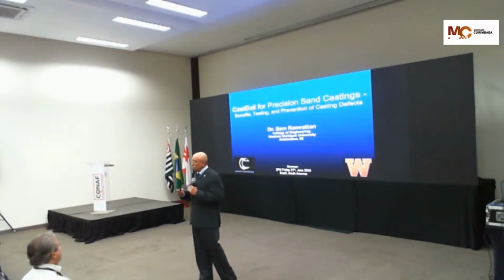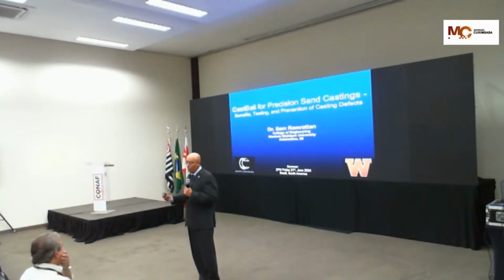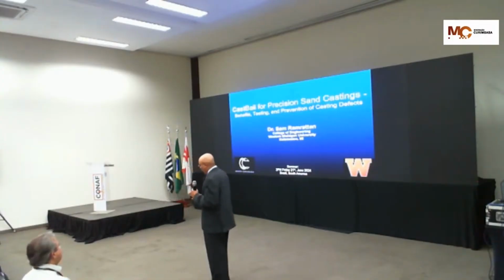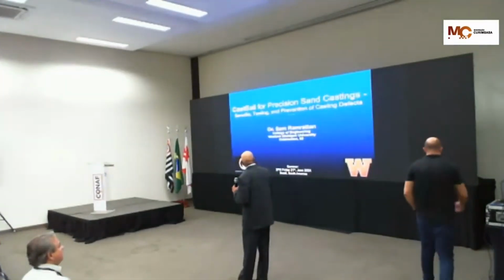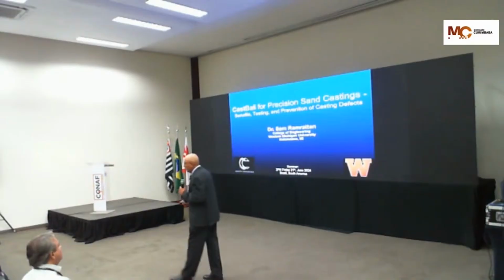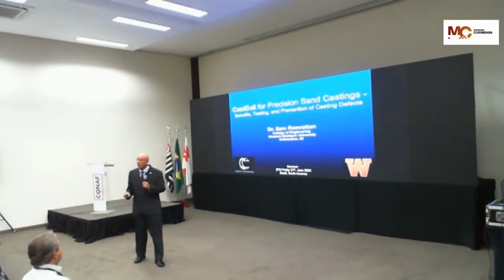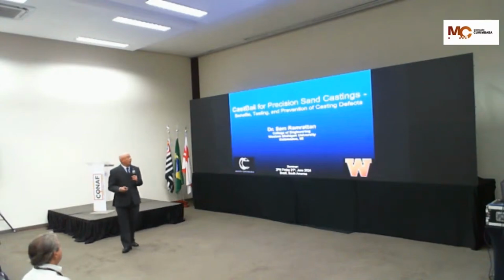However, the issue of strong indicates a mechanical property for a chemically bonded sand, but what is strong at ambient or room temperature may not necessarily be the case at elevated temperature. And for that reason, I have to describe some of the benefits, the testing, and then the prevention of casting defects relative to these precision sand systems. These defects come back to haunt us ultimately in the finishing room, where it drives up the cost for us to do our business.